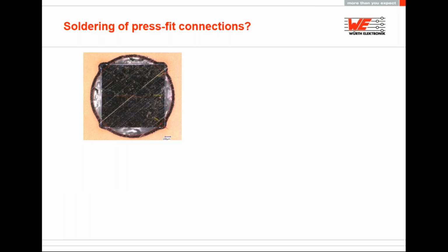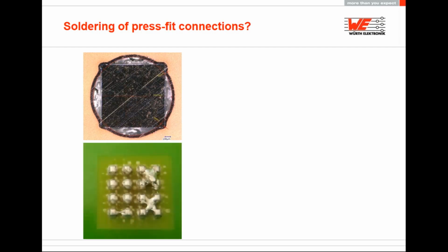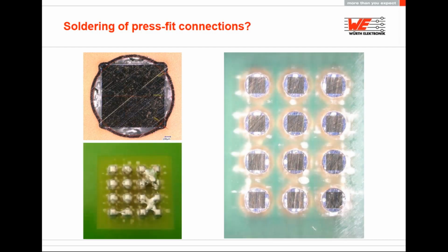So should you consider soldering the press fit connections? It sounds like a good idea, right? But it actually isn't. By soldering the press fit connections, most of the benefits of the press fit technology will get lost. The contact resistance, the mechanical strength, and all the other advantages that we saw in the beginning will get lost. Due to the volume of the REDCUBE press fit elements, it is hard to bring it to an overall temperature that allows a good solder joint. And it takes away heat from the process.